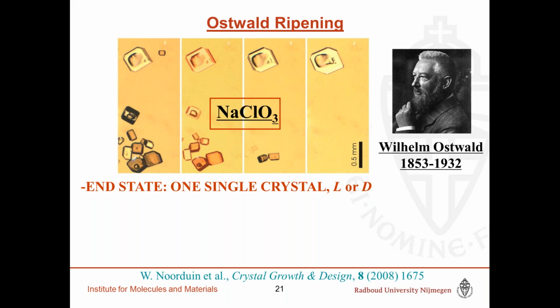Of course, kinetics, so the ways you want to get the crystals, like applying a high supersaturation or shock cooling or whatever, can sometimes help to get this metastable phase. But if you always get the racemic compound or the amorphous solid, then the chance that the racemic conglomerate is near to the racemic compound in energy, I would say, is not so very high.